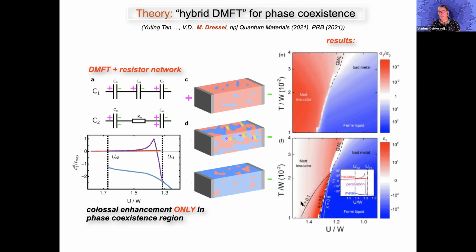That's right. In these organic materials, you have these big molecules, whose wave functions are weakly overlapping. When you apply pressure, the overlap increases, and there are DFT calculations demonstrating that the bandwidth is increasing. This is well represented by a single half-filled band, and by increasing the bandwidth, you're basically increasing the Fermi energy of your system while keeping the filling at 1/2. Thank you. Okay, very good.